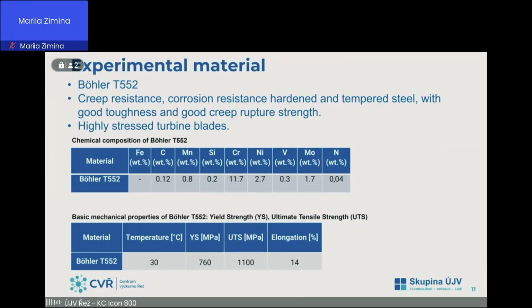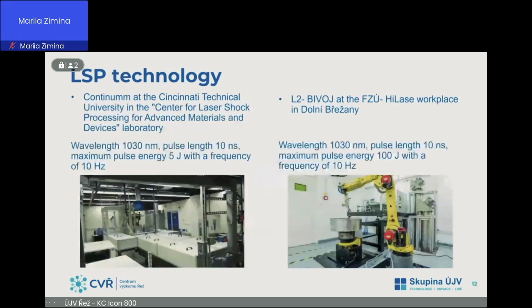The second material was martensitic stainless steel, which is used for highly stressed turbine blade with good creep resistance, corrosion resistance, hardened and tempered steel, with good toughness and good creep rupture strength. And the mechanical properties of the material is yield strength 760 megapascals and ultimate tensile strength 1100 megapascals.